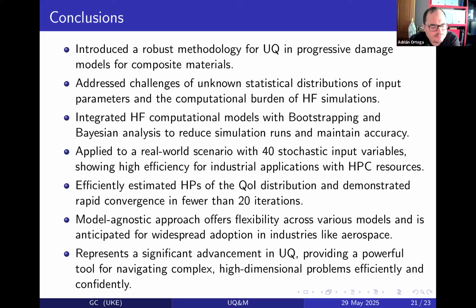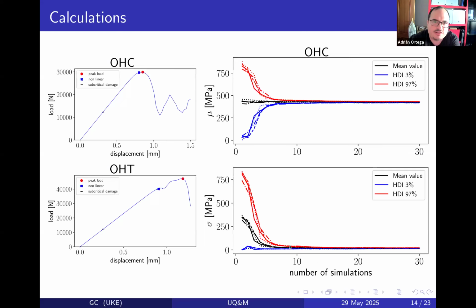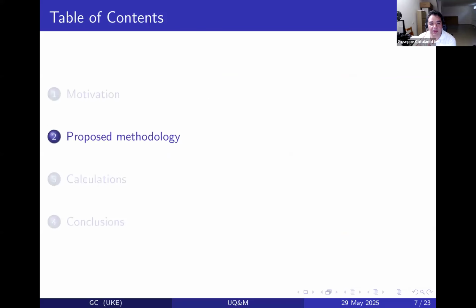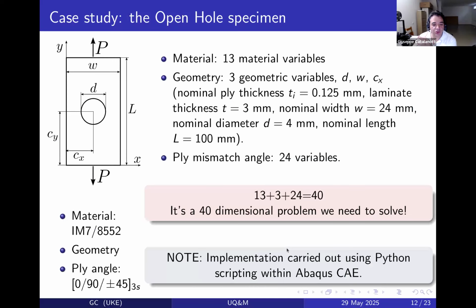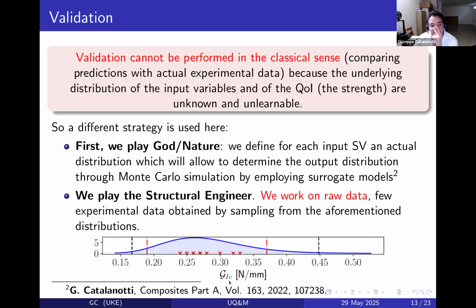I was wondering, if you have very few experimental points, and for example, in your results you're showing, when you are bootstrapping your properties, how many experimental points do you have in your database? For a given property, in my paper this is explained, in the sense that I made several assumptions. For example, I show you here maybe. Okay. For example, for this GFC, which is intralaminar fracture toughness in compression, I have 1, 2, 3, 4, 5, 6, 7, 8. Usually you have between 8 and 15, because this is a very peculiar test to perform. There are other properties where I have assumed to have more.